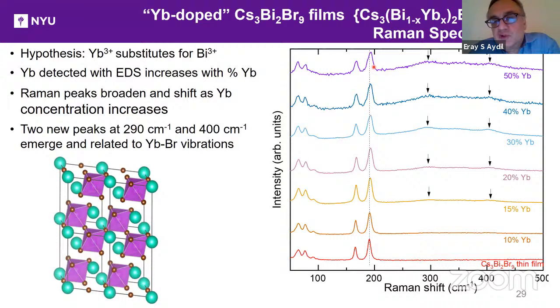And the broadening you would expect as you make the locations of the bismuth bromine vibrations more heterogeneous. So, for example, if you substitute in ytterbium for some of them, this bismuth bromine vibration would be different than one where it's not near an ytterbium substituted octahedra. In addition, we see two additional broad peaks appearing with ytterbium, which we attribute to the ytterbium bromide vibrations at 290 and 400 wave numbers.